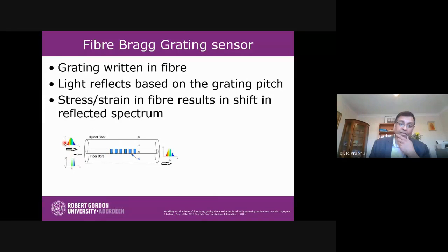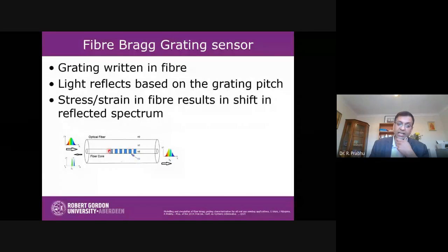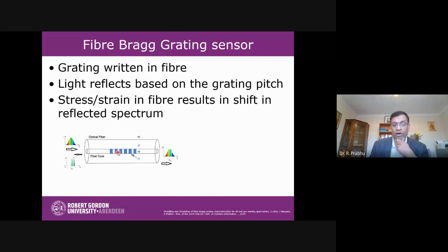If you use a broad light source, a small band of light will be reflected back, and that depends on the structure of this grating, or the distance between the gratings and the refractive index. If anything is changing in this region, that will result in a shift of the reflected spectrum, and that can be used for monitoring or for sensing strain or temperature around this region.